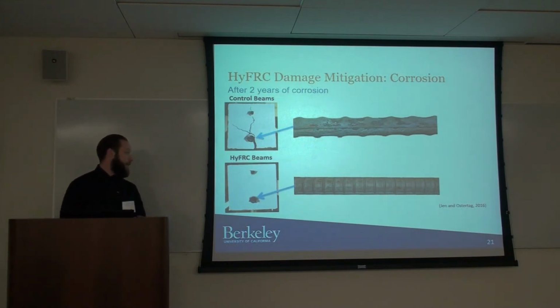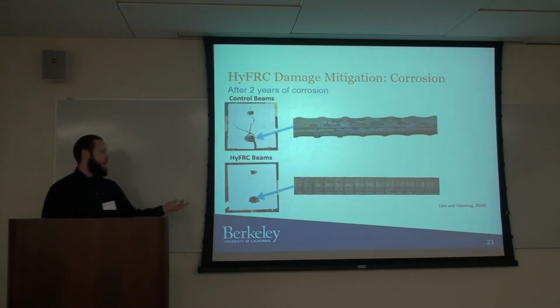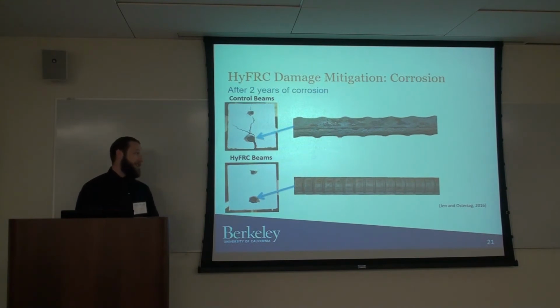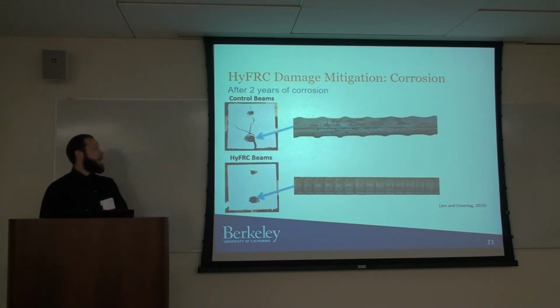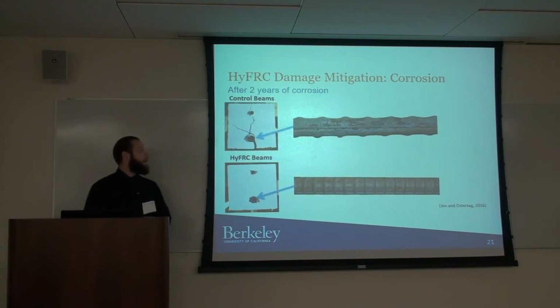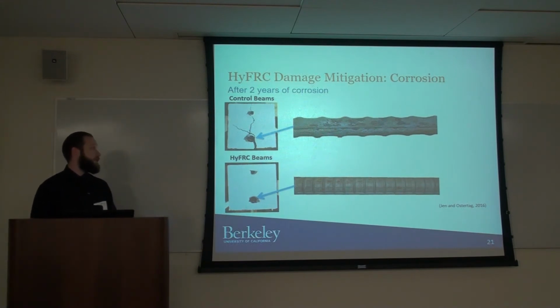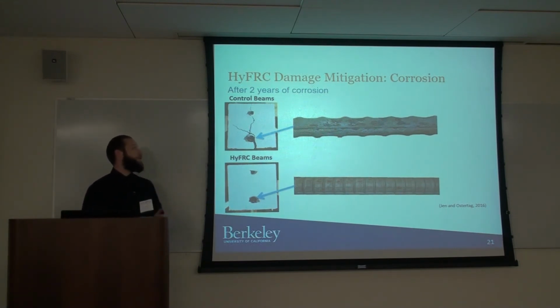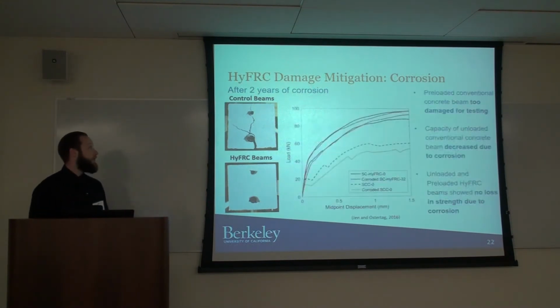The hybrid fiber reinforced concrete beams eventually depassivated and entered the propagation phase, but no significant damage occurred over the 2-year period. Meanwhile, in the control specimens, they completely split open due to splitting cracks from corrosion. Their initial cracks were transverse and some splitting from the flexural tests, but this damage, for example, the column being split in half, was done due to corrosion damage.